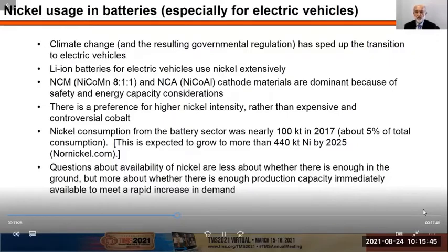Nickel consumption from the battery sector was nearly 100 kilotons in 2017, at that stage about 5% of total consumption. And according to some studies, this is expected to grow to more than 440 kilotons of nickel by 2025. Questions about the availability of nickel are less about whether there is enough in the ground, but more about whether there is enough production capacity immediately available to meet such a rapid increase in demand.